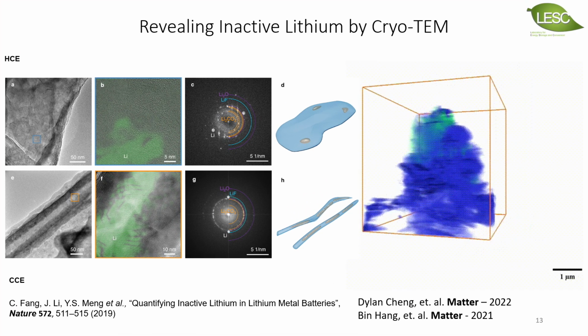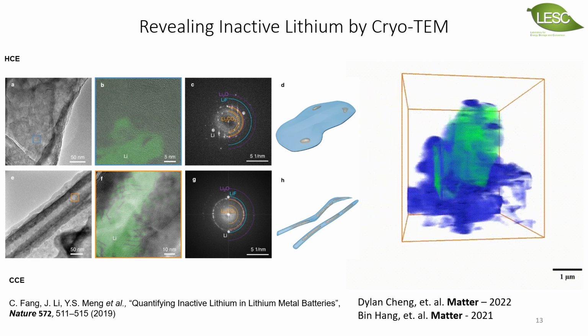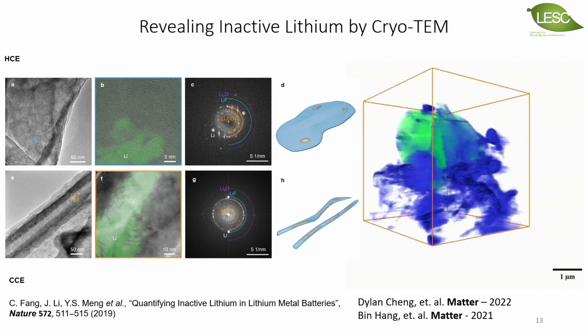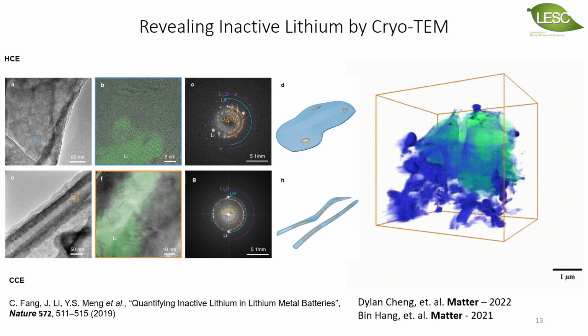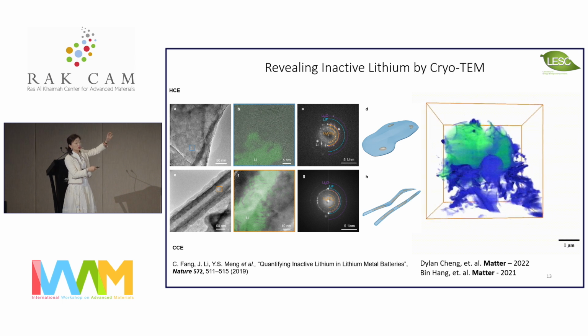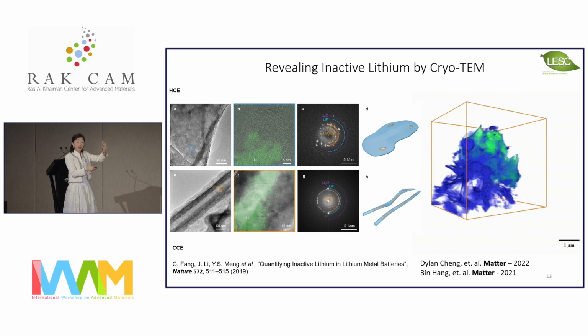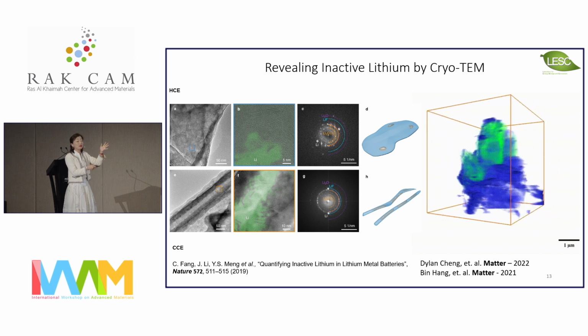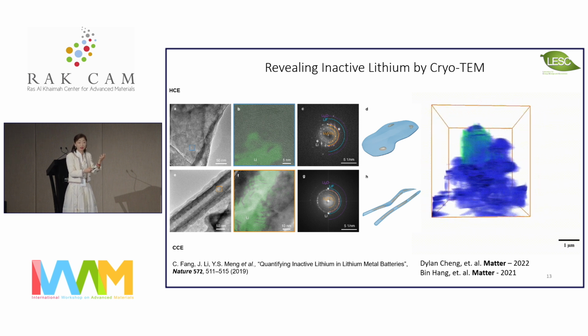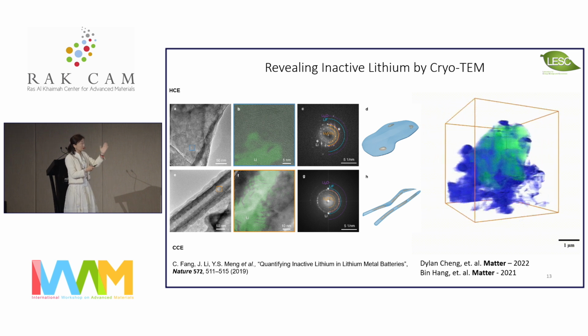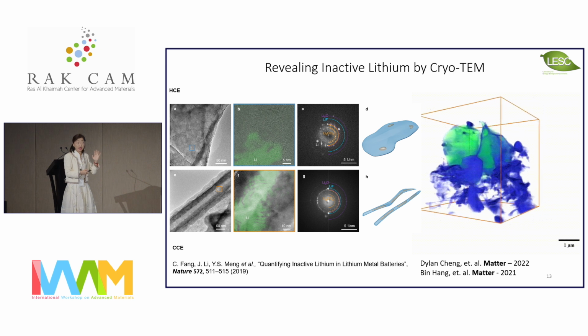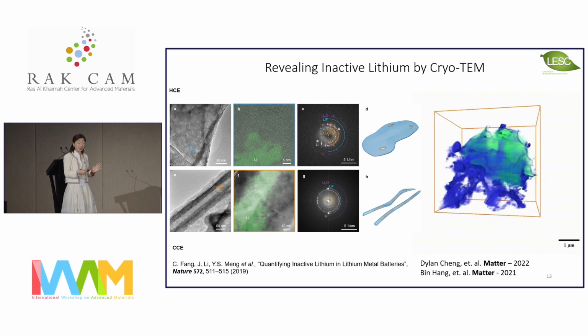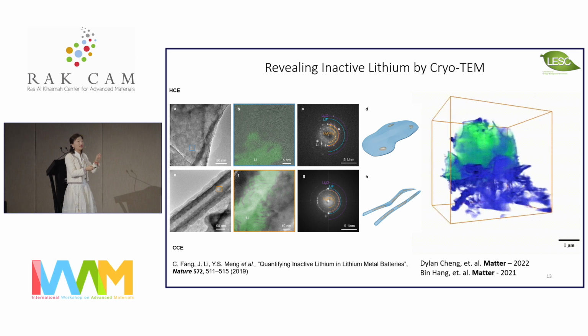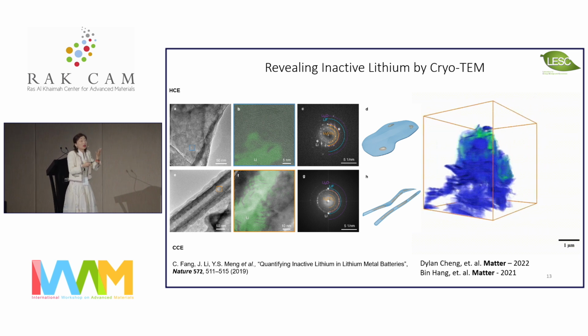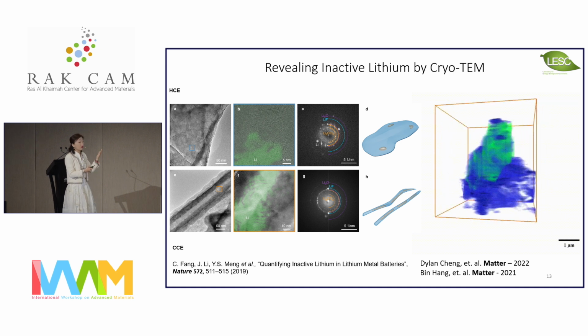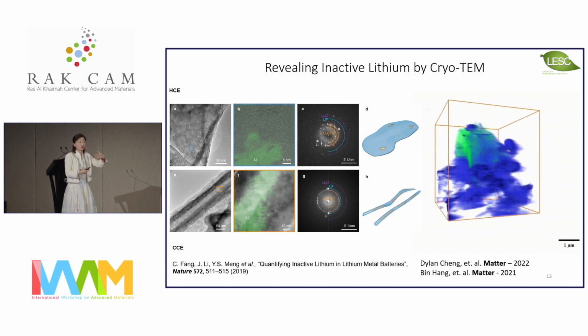And even more exciting is we can do tomography with X-ray or with electron. And this is the lithium metal that is completely surrounded by this solid electrolyte interphase. So lithium metal itself is conductive, but this blue layer of SEI is insulating. So under the microscope, being able to differentiate this gave us the first hint that a lot of the failure mechanisms in lithium metal batteries are caused by what we call electronically isolated lithium. So it cannot participate in the battery operation because it lost its connection to the electron, to the current collector.